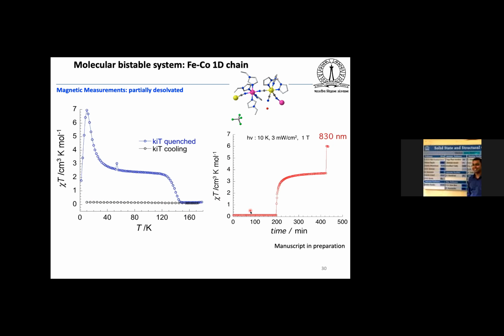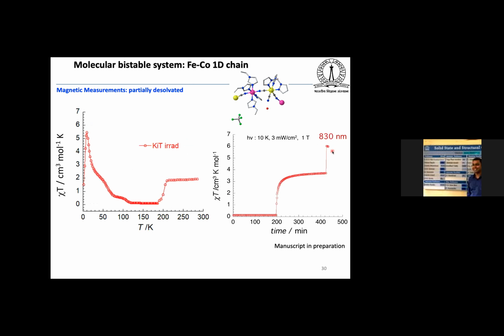And at low temperature, at 10 Kelvin, we irradiated the system, and you can see the system is converting completely from the diamagnetic to the paramagnetic state. And then the system is relaxing back. This photo-induced metastable state is relaxing back at approximately 120 Kelvin. And again, when you increase the temperature, we can observe metal to metal electron transfer taking place. And you can see only half of the molecules are converting to the paramagnetic state.